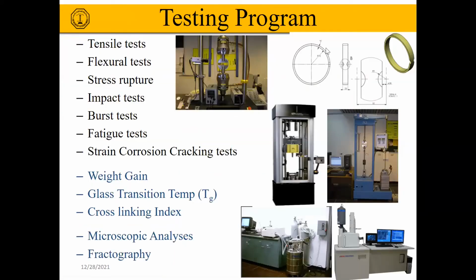And every period of time, we would pick up the specimens, which are ring specimens, and test them. We look at the tensile properties, flexural, stress rupture, impact, low velocity impact, burst tests, fatigue tests, and strain corrosion cracking tests. We also measure the weight gain, glass transition temperature, and the cross-linking index. And we look at their microscopy, and we look at the fractured surfaces to see what the mechanisms of fracture are.